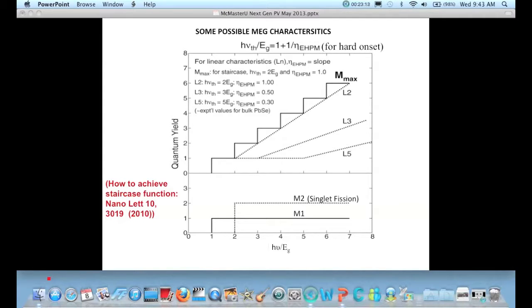Now, there are various characteristics that could be conceived. One is the ideal case where every time the photon energy is n times the band gap, you get n electron hole pairs, or n excitons. And as the photon energy increases, you would get a staircase type function. So I'm plotting the quantum yield of electron hole pair production versus normalized photon energy, which is how many band gaps of energy you're exciting with. But until recently, we were just beginning to close in on this staircase type behavior.